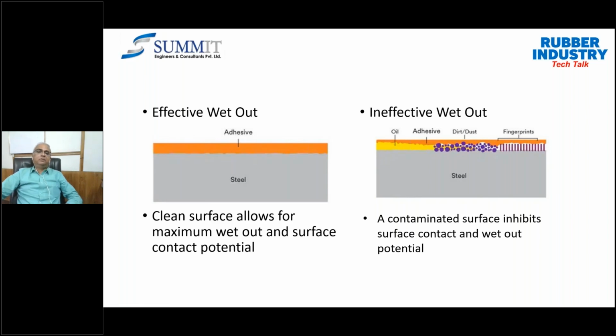I also just described the lower surface energy part of it, right? So these low surface energy elements or the rubber components, what do you mean by low surface energy? The best method is to put one drop of water onto the rubber element. If that drop remains as it is over there without any dispersion, it means this material or this rubber has got less surface energy. If there is a bigger or greater surface energy, what will happen? That droplet which has been put onto the surface will spread out, and this spreading is nothing but your better surface energy.